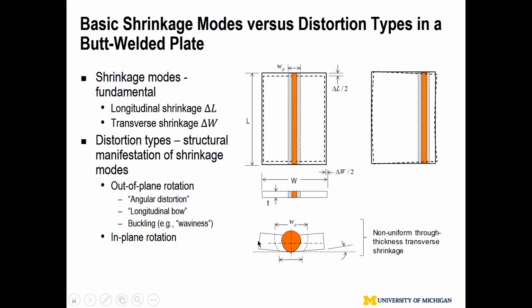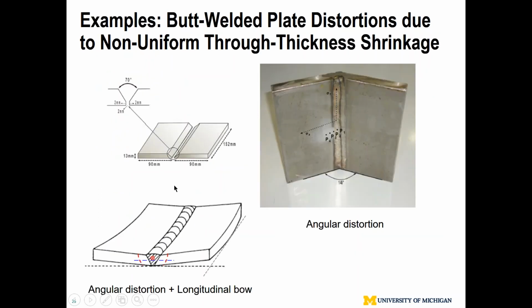But the problem is, when we talk about distortion, that means the shrinkage no longer has symmetry to work with. In that case we can have out-of-plane distortion, rotation, angular distortion, longitudinal bow, buckling, and then in-plane rotation. If the seam is located away from the symmetry, you have an in-plane rotation. If a big blob of butt seam weld gets deposited and the dashed line is not symmetric to the neutral axis of the mid plate thickness, you have angular distortion.